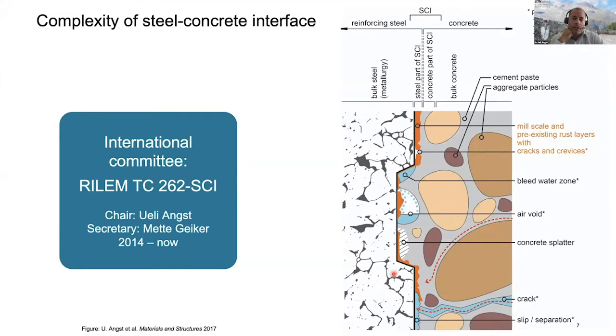This sketch here stems from an international committee, a RILEM Technical Committee, that looked into the steel-concrete interface in the last couple of years. You can see the schematic sketch here that shows on the left-hand side the steel part of the interfacial zone, and on the right side the concrete part of this interfacial zone. And you can see considerable heterogeneity along this interfacial zone. So the steel may be covered with mill-scale or native rust layers, which may also be cracked. Then we may have regions due to geometry where we have bleed or settlement zones, where we could have macroscopic voids in the concrete, interfacial voids. We can also have entrapped air voids, for instance, or cracks, and all these macroscopic voids may be water-filled or not, so they may just be partially filled, as I mentioned before, and that, of course, can be important.